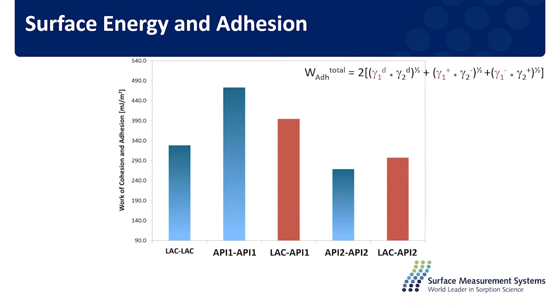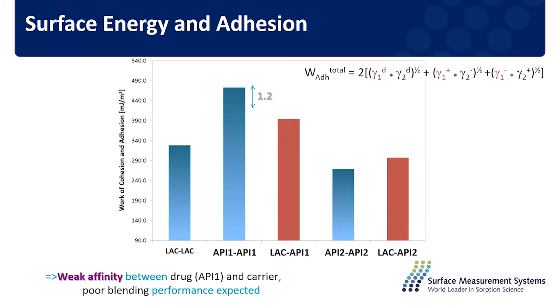So here are the results of the cohesion and adhesion. The blue blocks are the cohesive energy, the red blocks are the adhesive energies. You can see the equation for how the work of adhesion is calculated from the surface energy. The surface energy values of components 1 and 2 are used to get this adhesive energy. The cohesive energy is similar, but in that case only one sample's surface energy is used. The cohesive energy of API1 is really high compared with the adhesive energy with the lactose. In this case, because the ratio is about 1.2, we can tell that there's a weak affinity between drug and carrier. So we expect poor blending performance, because API1 has a higher affinity to aggregate with itself and not to interact with the lactose.